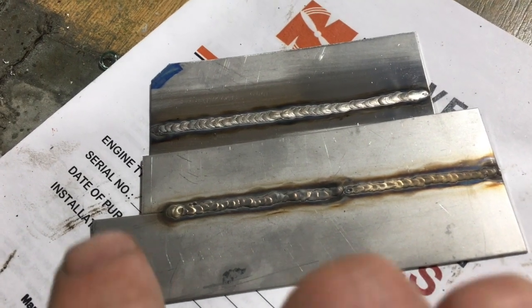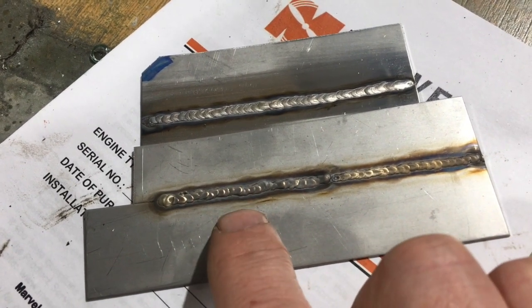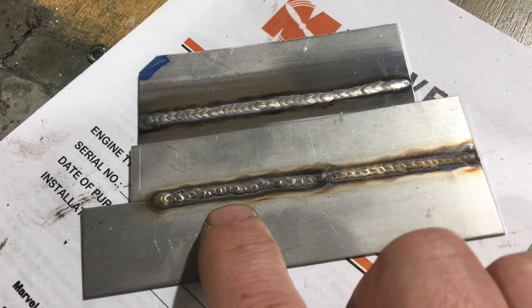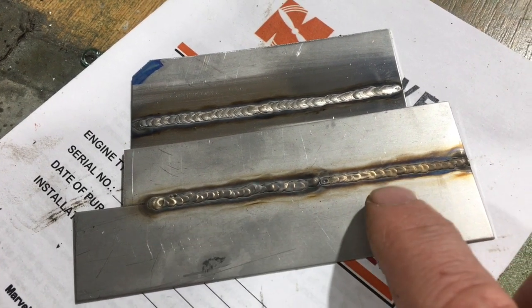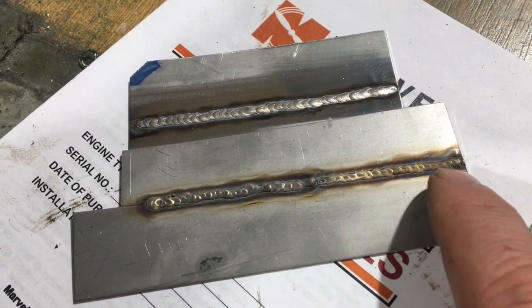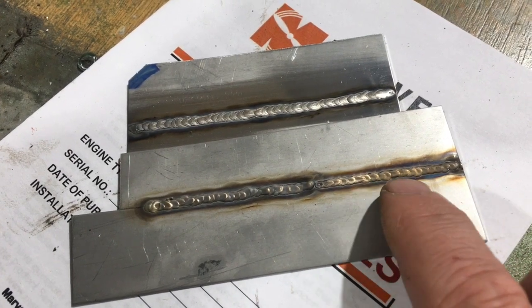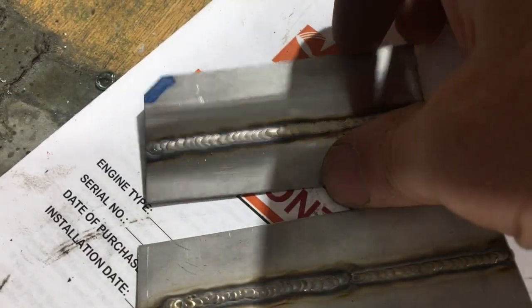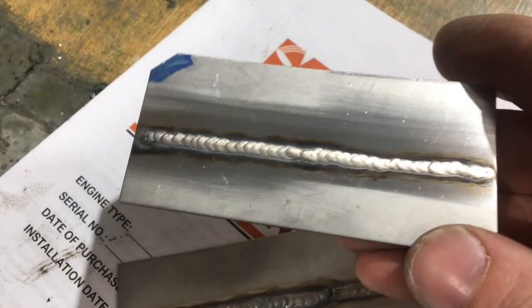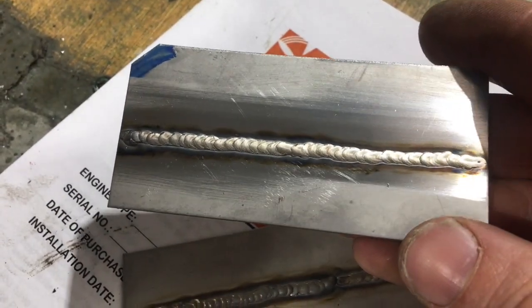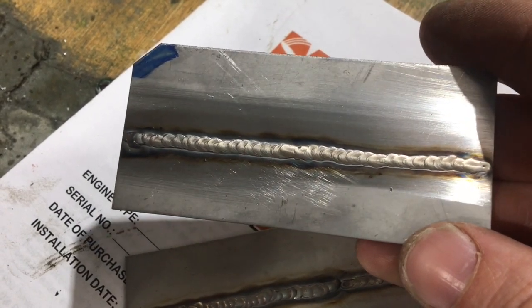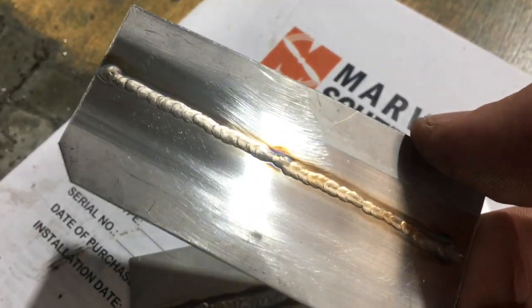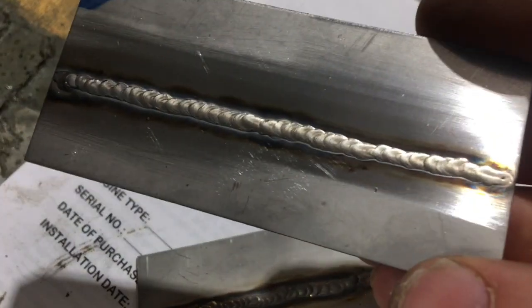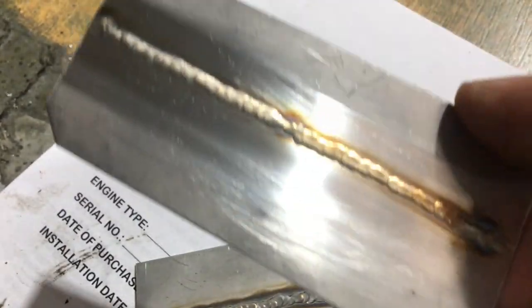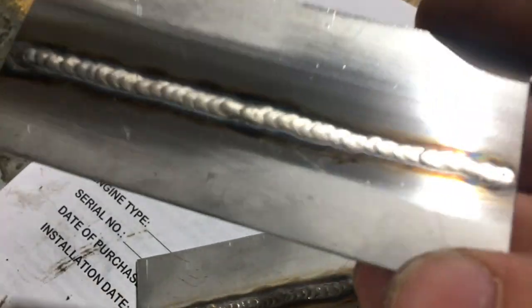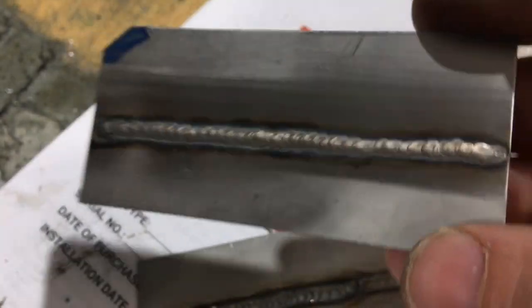Alright, so we are beginning to get somewhere near where we want to be now. This one too slow. This one the faster travel speed. So that's a good example of the more amps, less heat input, because it gets you moving quicker. But this one, this last one with the Furick cup, gas coverage, top and bottom, both sides of the sheet were much better. The weld is shinier, the penetration is smoother. We'll get a look at this in a minute in some daylight. That's probably going to pass you a test. That's closer to where we want to be.